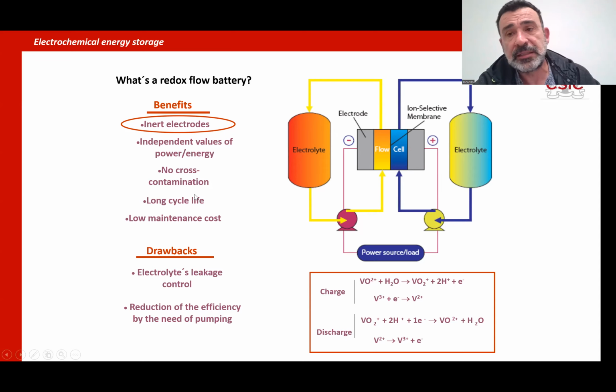A lithium-ion battery lasts 1,000 charge cycles. Here, we are talking about 10,000 cycles, okay? And the most important property of this system is that they have independent values of power and energy. The energy is in the electrolytes. If you want more energy, what you need is to put more electrolyte, larger tanks. Then you can store 1 megawatt, 100 megawatts of energy, depending on the size of the electrolytes. While power depends only on the electrochemical cell, on the electrodes, how fast the electrodes are having the reactions.